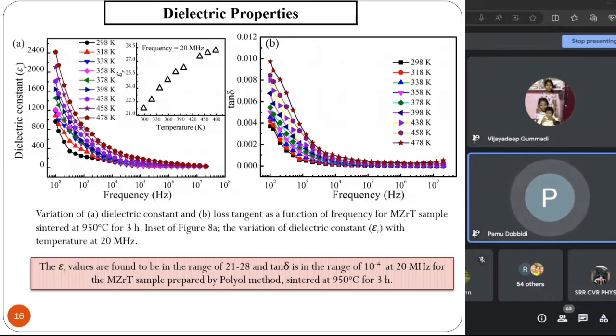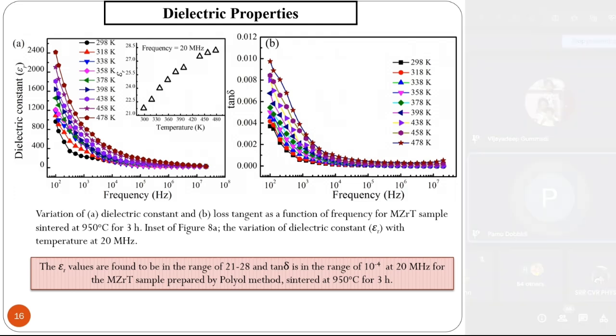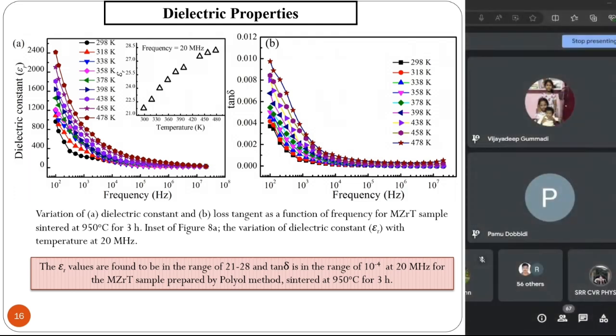Yeah. So why did we do this measurement? These are done at low frequencies. In order to do these measurements, we need a parallel plate capacitor. That means you make a thin ceramic disc or pellet, and on both sides you apply silver paint, and then do the measurement. When you do that, the dielectric constant seems to be very high, naturally, because your electrode contribution is there, and this is at a low frequency. Just for curiosity, that is where the dielectric constant seems to be higher, and the loss tangent also seems to be higher here. Why?